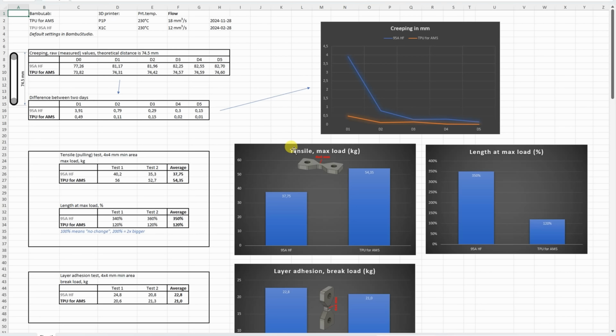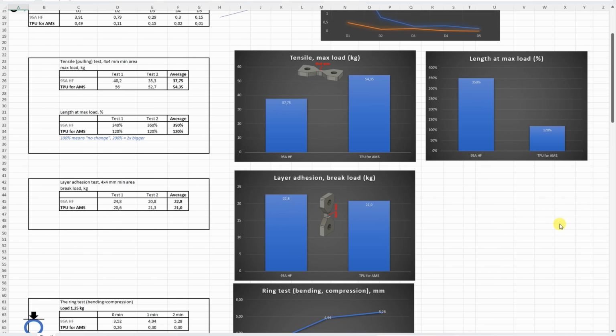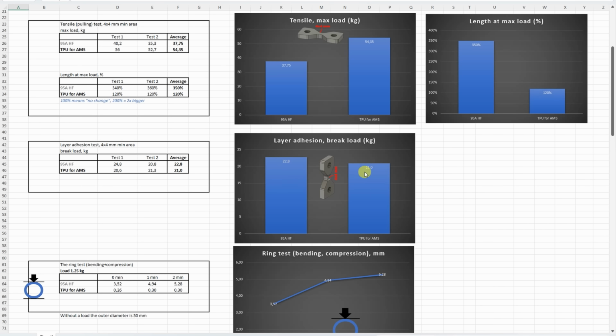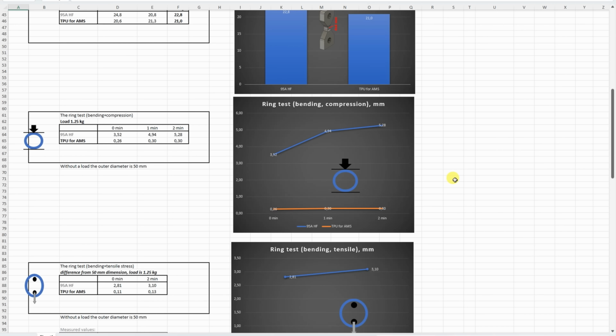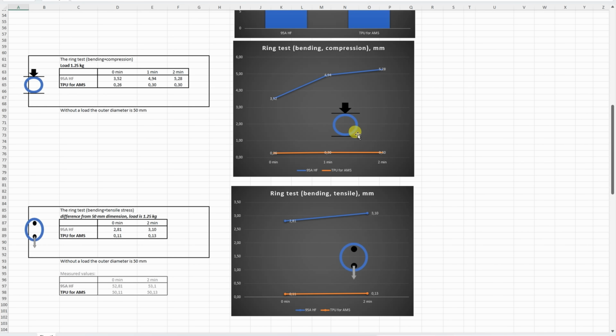And just quickly to analyze the numbers, and I included here the results for TPU 95A for better comparison. On the creep test, we can see that this TPU for the AMS has a very minimal creeping. For example, it is good for the timing belt. I presented this in a separate video. On the tensile test, it is slightly stronger, but also it broke on small deformation. On the layer adhesion test, no big difference here between these two materials. On two ring tests, definitely we can see much lower deformation on TPU for the AMS compared to the 95A.